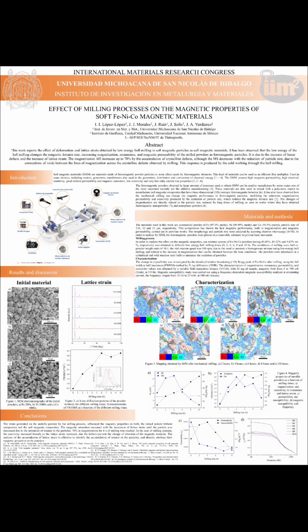For their magnetic behavior, in the case of the milling process, in order to analyze the effect on magnetic properties, one mixture system of iron, nickel, and cobalt having 45, 45, and 10% respectively was obtained at different low energy ball millings from 0 to 10 hours with a step of 2 hours. The milling conditions were a ball to powder weight ratio of 10:1 and a vial rotation speed of 100 revolutions per minute, due to the need to promote a homogeneous mixture using low energy ball milling. The powders were introduced in a cylindrical vial with stainless balls to minimize the oxidation of particles.